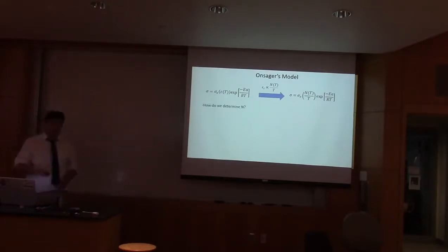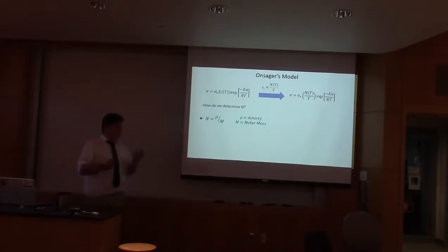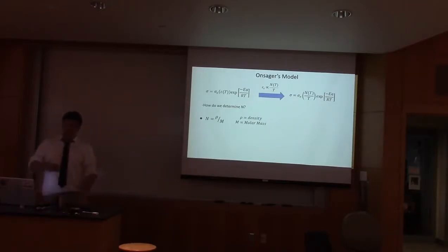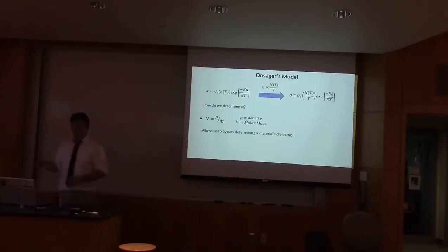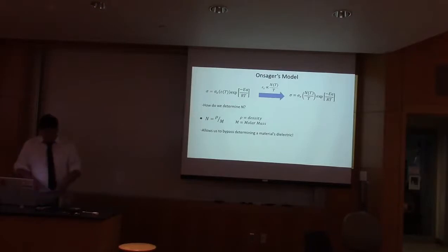So how do we determine n? Why is this significantly better for us? Well, the dipole density itself is just pretty much equal to the density divided by the molar mass. If you think about this, we are basically determining the amount of molecules per given volume, and if we assume there is one dipole per molecule, we have how many dipoles there are per unit volume. This allows us to completely bypass determining a material's dielectric constant, and it has proven very useful in studying room temperature ionic liquids in the last couple of years for Allison's research group.